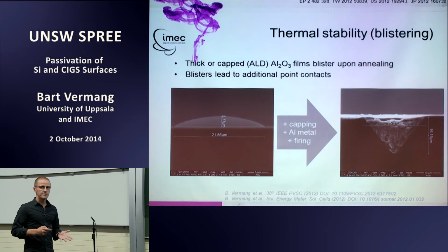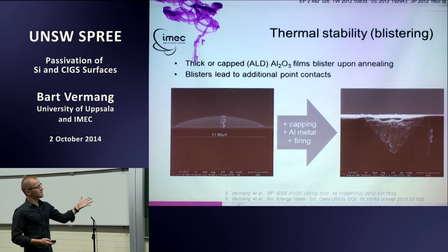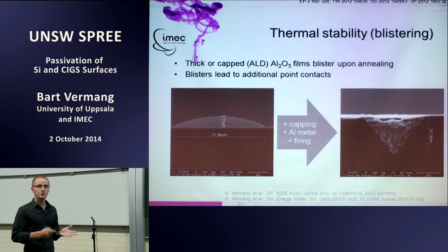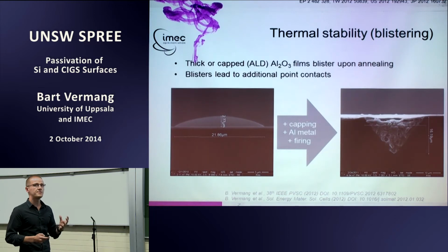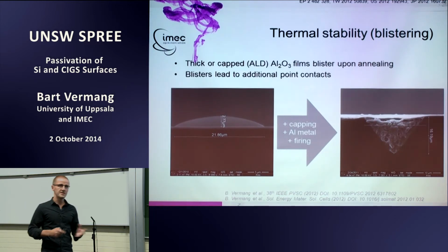And in PERC or PERL, typically we're still using co-firing processes. So if we bring it to a very high temperature later, you might create extra local contacts. And extra local contacts also means less passivation. It means more contacting, but you lose part of your passivation. So blistering, because of that reason, is not a good thing, and in ALD it happens earlier or easier, because ALD is typically deposited at a low temperature. It's 300 degrees, 250 or even 200 degrees in the silicon PERC case. So at a lower temperature, first of all, and there's no plasma involved. If there's a plasma involved, your layer is typically a bit more dense as well, which also prevents blistering at lower temperatures.